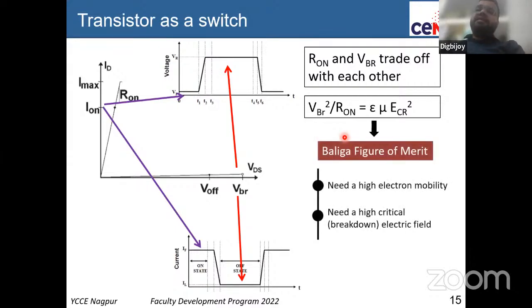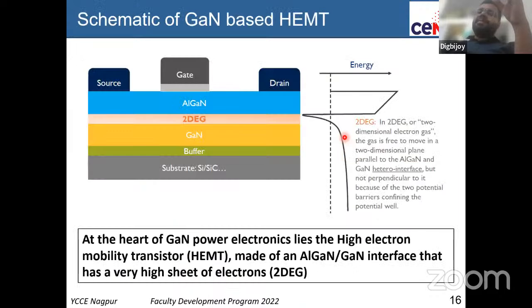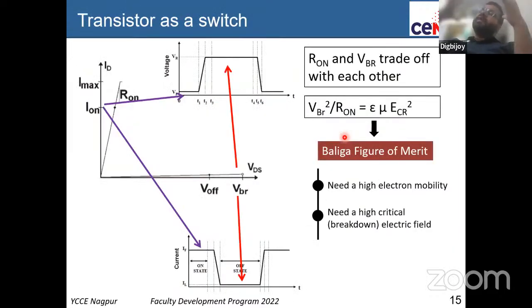Okay. Now this Baliga figure of merit is a constant for a given material. So for silicon, it is a certain value. For gallium nitride, it is a certain value. What happens is that in gallium nitride, this Baliga figure of merit depends on critical electric field and on mobility, which are superior in gallium nitride than silicon. What it means is that the Baliga figure of merit for gallium nitride is much better than silicon. What it means is that for the same on current in gallium nitride, you can get much higher breakdown voltage than silicon. So this is a great advantage.